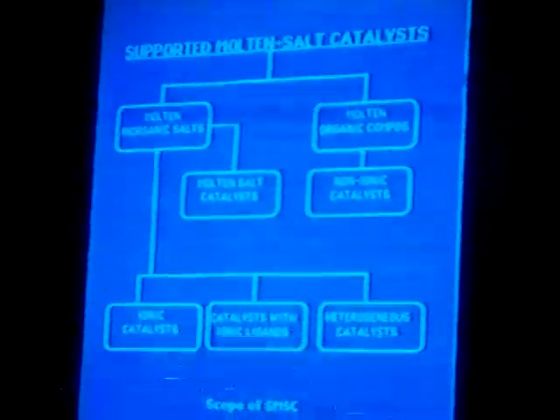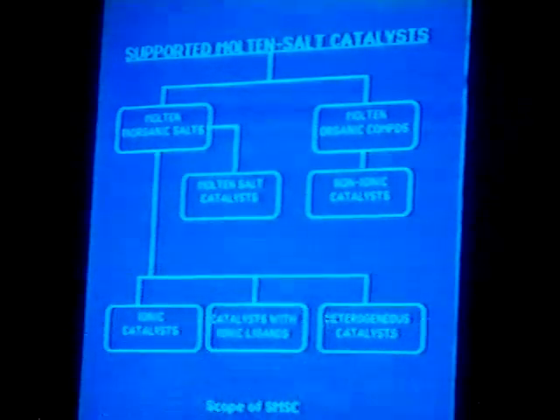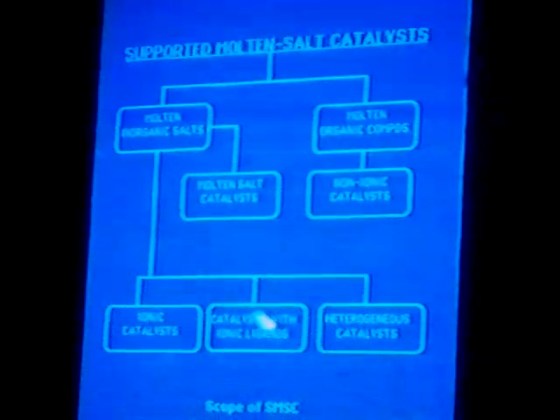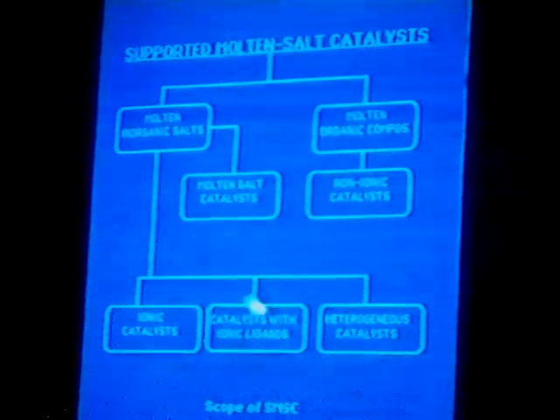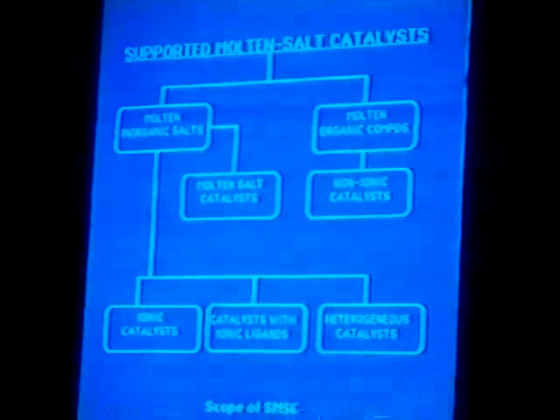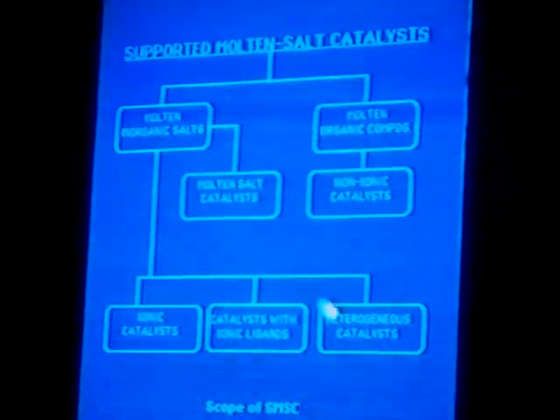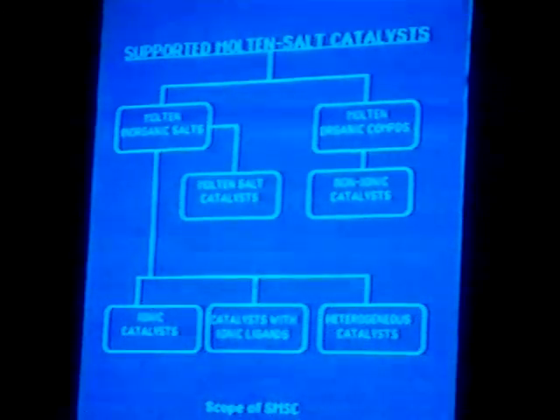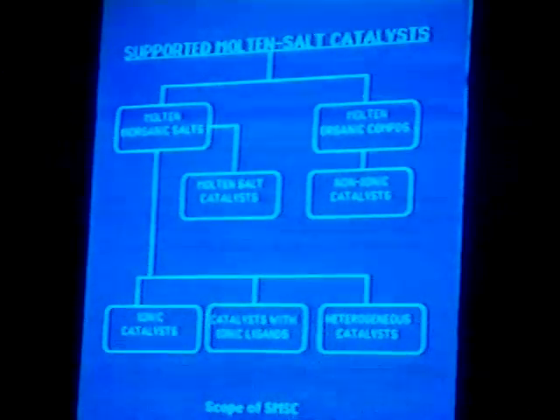This slide gives the overall scope of the supported molten salt catalyst technique. Depending upon whether the molten salt is ionic or not, you can dissolve an ionic homogeneous catalyst in an ionic molten salt. If the catalyst is not ionic, you can frequently change the ligands to make them ionic so they dissolve. Even some heterogeneous catalysts are soluble in molten salts. If you have non-ionic catalysts, you can use either molten organic compounds or those inorganic molten salts that are not ionic.